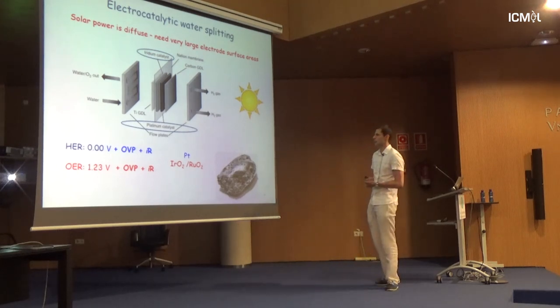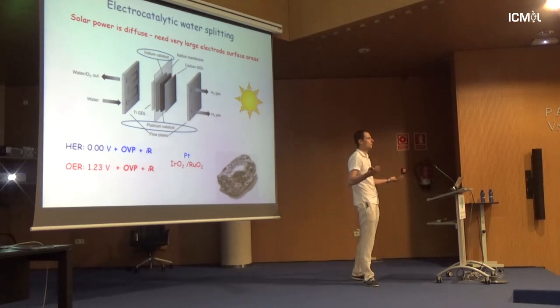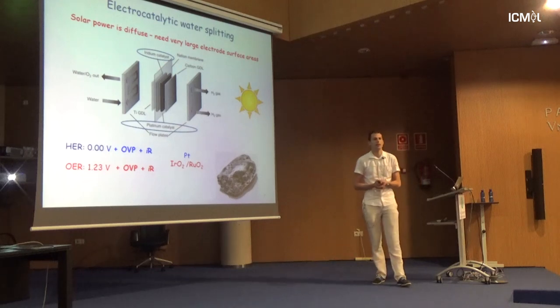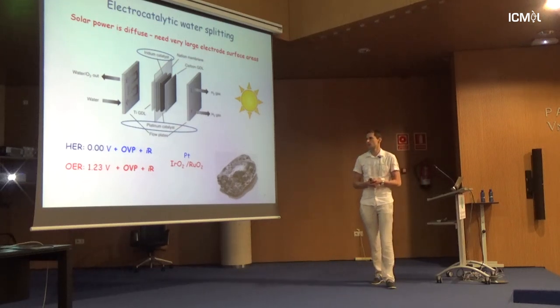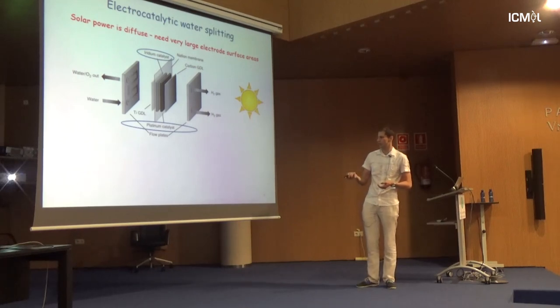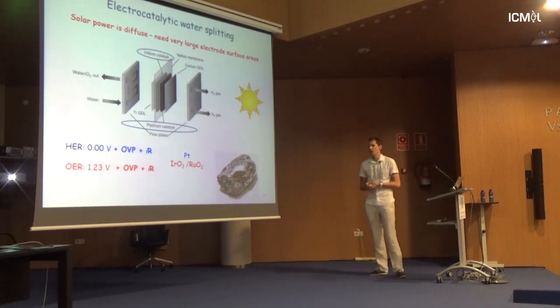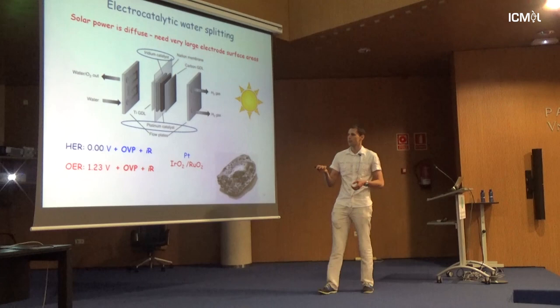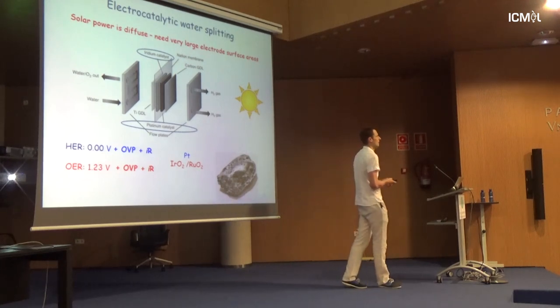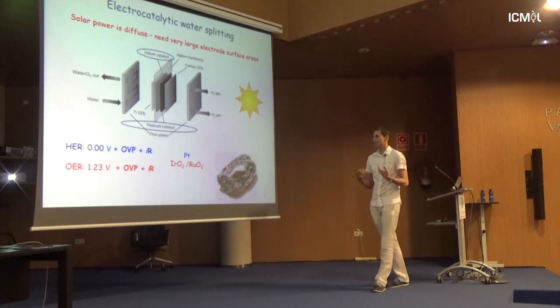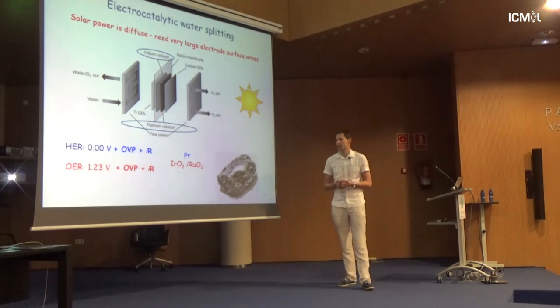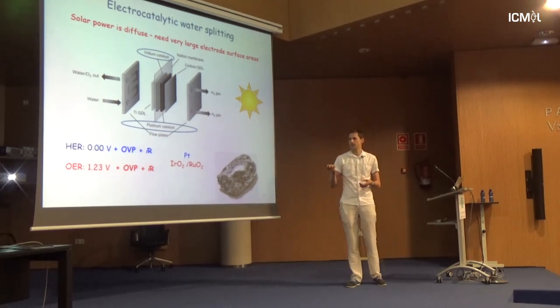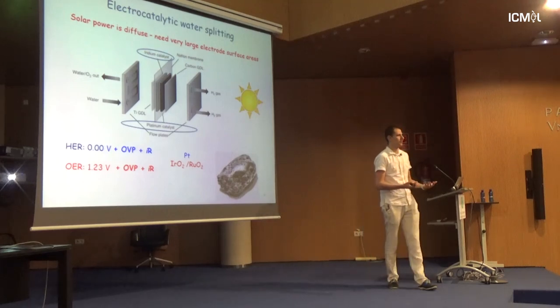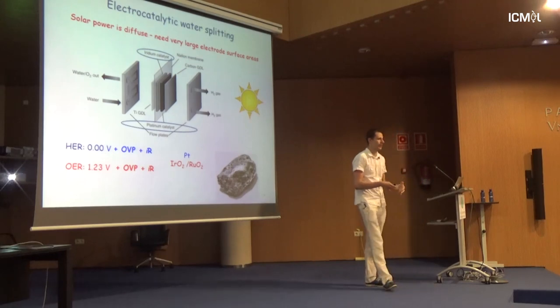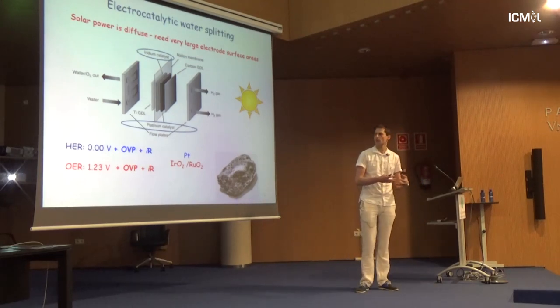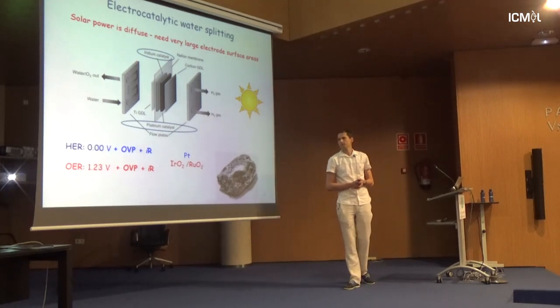So the obvious attempt for a chemist is to search for a new chemical system, or at least try to understand if there are any sustainable alternatives to these two brilliant elements, iridium and platinum. Okay, so what is very important to mention here, as I already said, the hydrogen evolution catalytic reaction in theory doesn't require any energy, but this is in theory. So what in practice we have is a surface effect. The hydrogen needs to adsorb on the surface, or protons need to be adsorbed on the surface of a catalyst. And they need to recombine somehow to molecules, and they need to desorb from the catalyst.